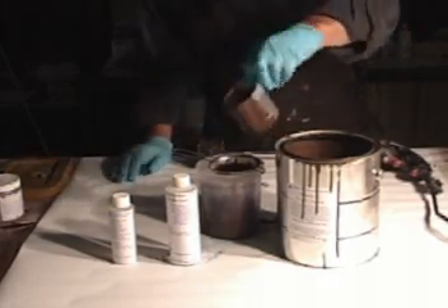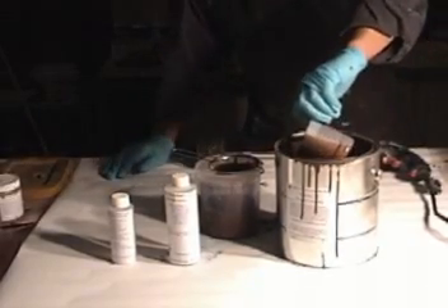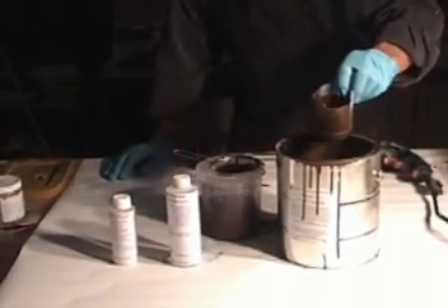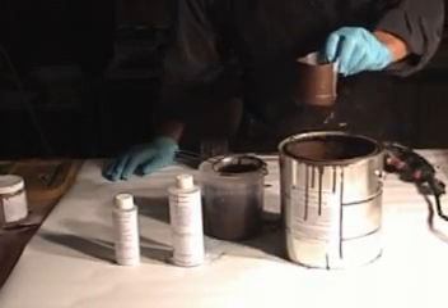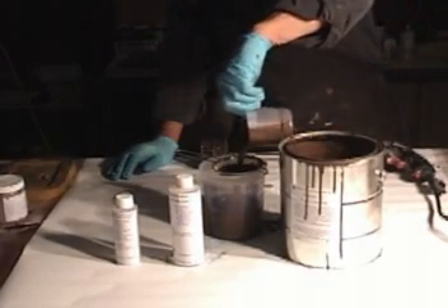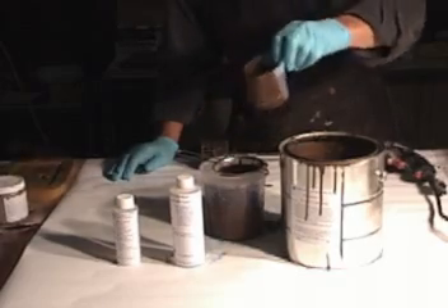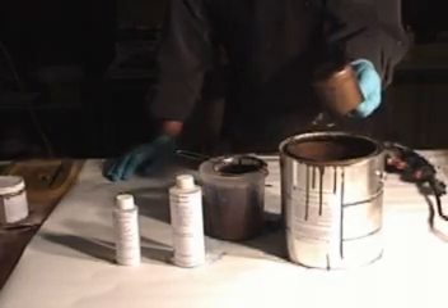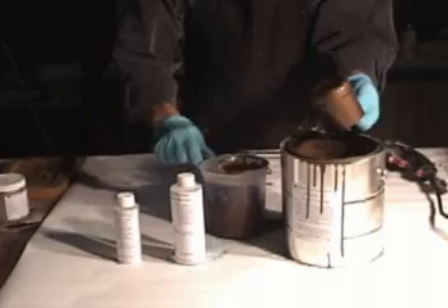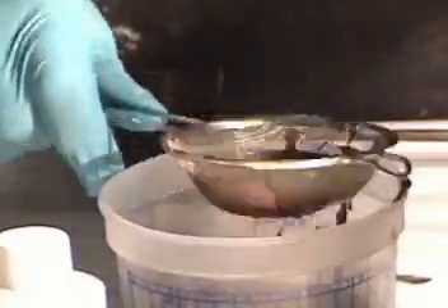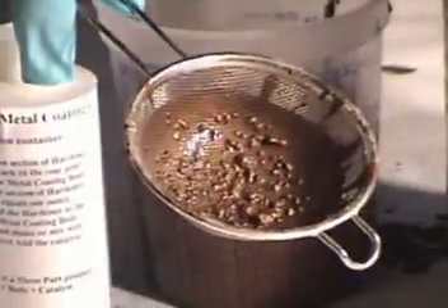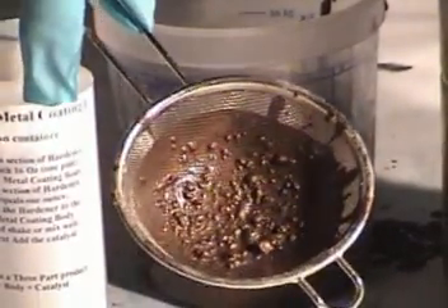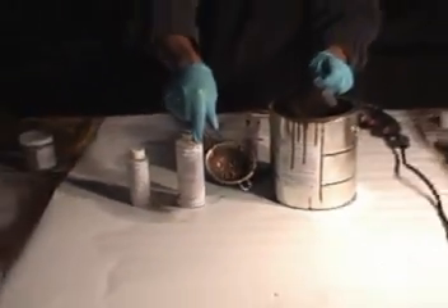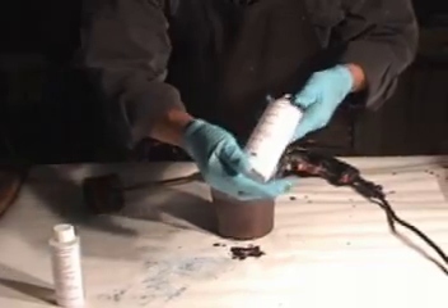Anytime you're using these metallic paints in a sprayer, like you'll see later in this video, it's very important to strain the paint to remove any lumps that might clog your sprayer later on. So you'll notice here we're using a stainless steel strainer to strain the paint base before we start. And we're measuring out about 16 ounces. And you'll notice that that amount will correspond with the tick marks on the side of the hardener bottle and the catalyst bottle. Now here you'll see Ron is showing all the little lumps and little goodies that were hidden in the paint. If we hadn't strained the paint, that would all be material that might clog our spray gun.